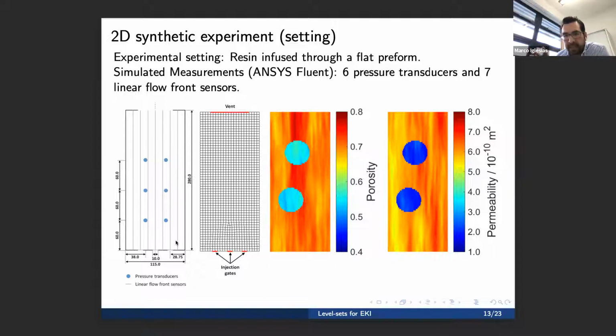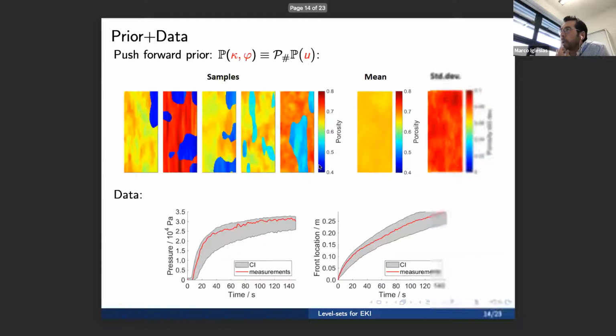So we solved this moving boundary problem using ANSYS Fluent to simulate these measurements from these sensors, using as a truth this porosity and this permeability. Assuming obviously they are in the same location, this is the effective area of low porosity, and adding some variability by producing some random fields. Now, the prior is a prior that we put on these hyperparameters and the right-hand side of the SPDE. And by pushing all these hyperparameters forward into physical space, we produce all these samples.